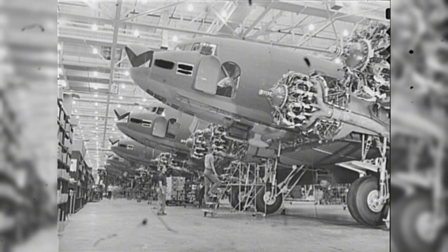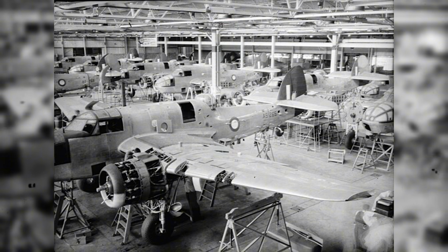This steel contained approximately 0.30% carbon, 0.80 to 1.10% chromium, and 0.15 to 0.25% molybdenum with no nickel. In the annealed condition, it possessed moderate strength, but when normalized and tempered, heated to 1,600 degrees Fahrenheit, air-cooled, then reheated to 1,100 degrees, 4130 steel achieved tensile strengths exceeding 90,000 pounds per square inch, matching many nickel steel grades. Engineers scaled up and requalified chromium-molybdenum steels such as SAE 4130 as substitutes for traditional nickel steels.